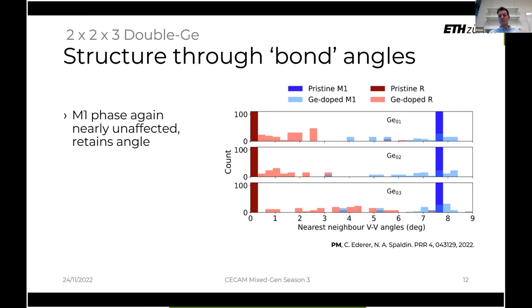But the rutile phase gets shifted away from the zero degree rotation that it had into some sort of distribution, which is strongest in the GE03 configuration, which leaves two vanadiums between to dimerize. And so we have a nice distribution.